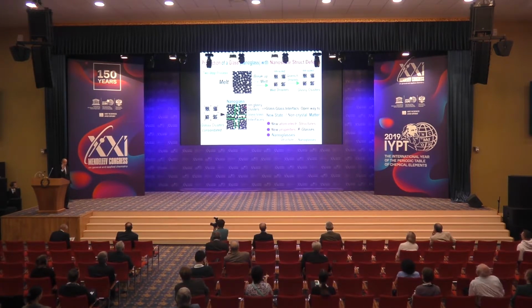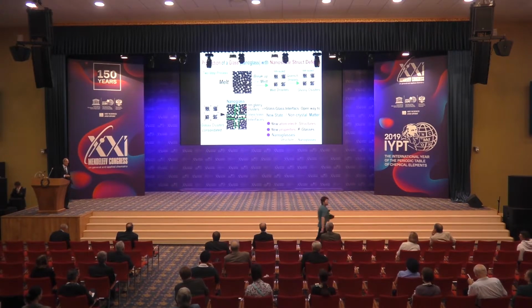So we have very tiny glassy clusters, and we take these glassy clusters and consolidate them at high pressure, several gigapascals, into a solid. These are the clusters, and these are the interfaces between these clusters, and this solid is called a nanoglass. A nanoglass because it has glassy regions of nanometer size. So it's like a nanocrystalline material, but not crystals, but glassy regions. And it's now the glass interfaces, or the atoms in these glass interfaces, that produce the new effects.